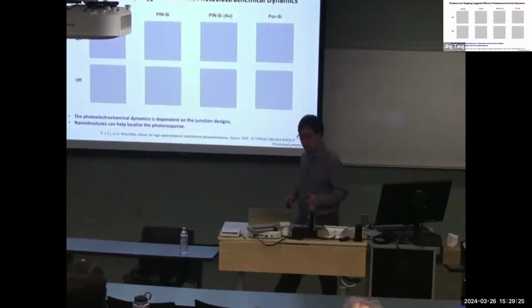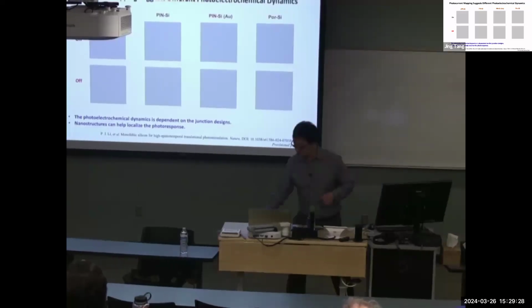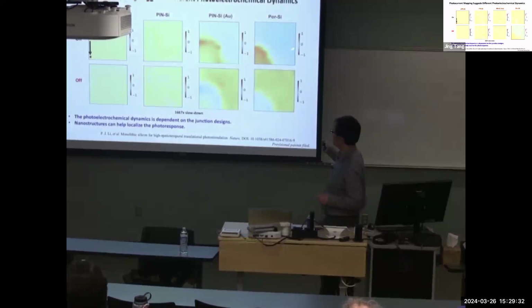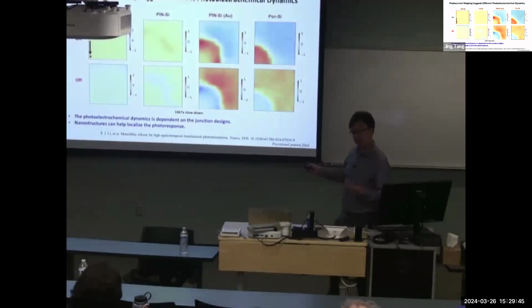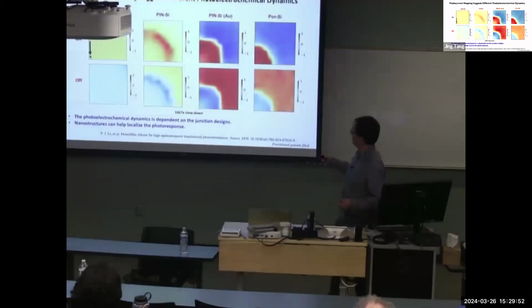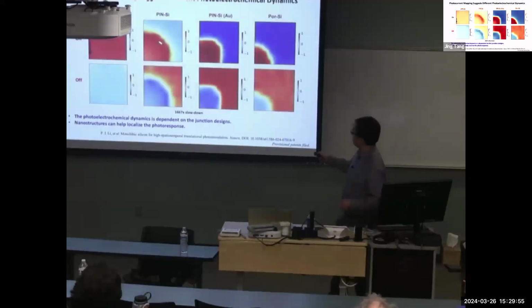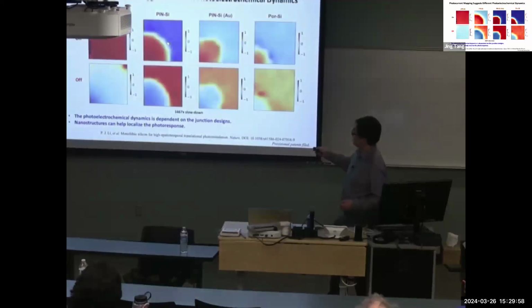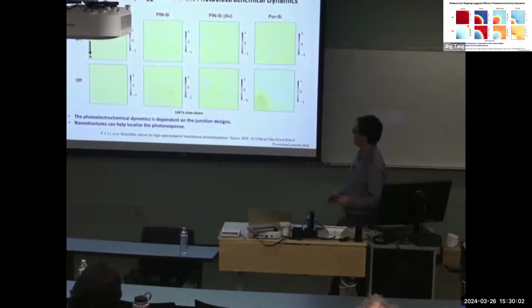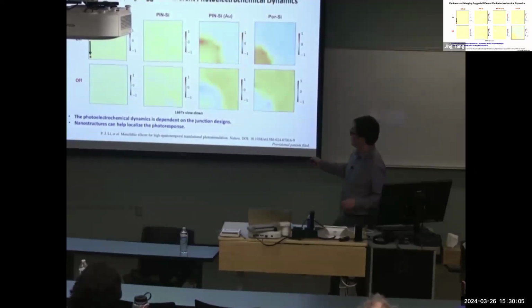But I just want to show you some photocurrent mapping results. In those mapping results that we collected from the 4 different materials, we shine light to the lower left corner of the silicon wafer. The silicon wafer dimension is about 4 millimeter by 4 millimeter, square-like. Shine light here. And what do you see here? The different colors represent different polarity of the photoelectrochemical current. Red means a cathodic current, photocathodic current, and blue means photoanodic current. If you see a boundary or even boundary evolution, that means there's a transition from one polarity to a different polarity. So the first takeaway message is that in terms of localization, this material is the best, as predicted by the minority carrier argument I made just now.